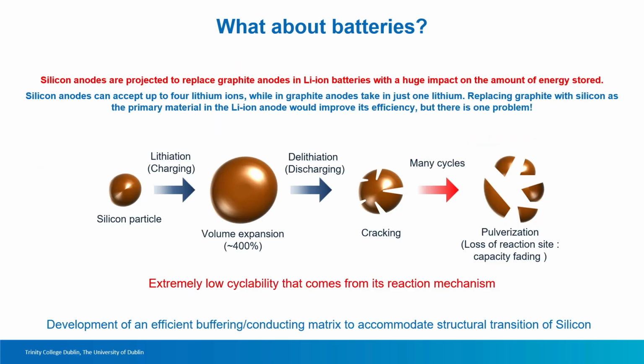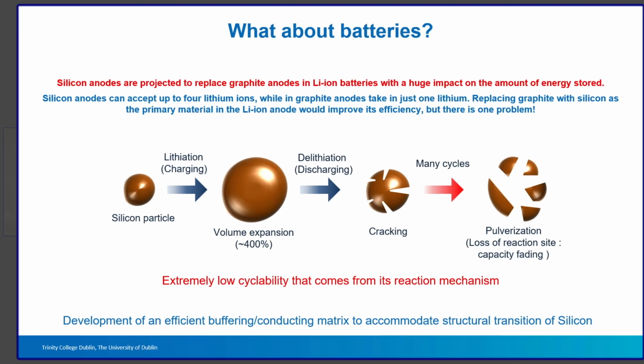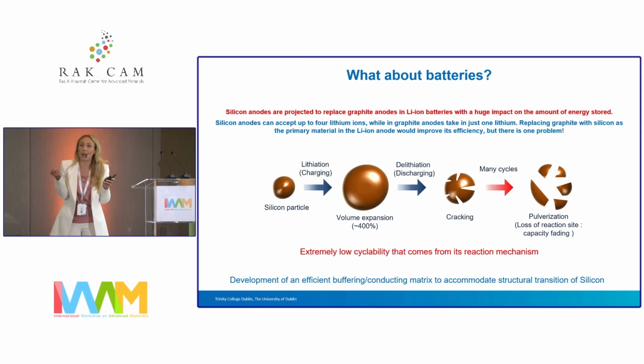decided to do in the first place was to start working with a very promising electrode material for the anode, which is silicon nanoparticles. It was a very well-studied anode material at the theoretical level. In practice, in pure form it only lasts probably about 10 cycles. The reason is that when you charge and discharge, the material goes through a volumetric expansion and then expansion of about 400%. And once you do it a few times, it becomes completely pulverized.